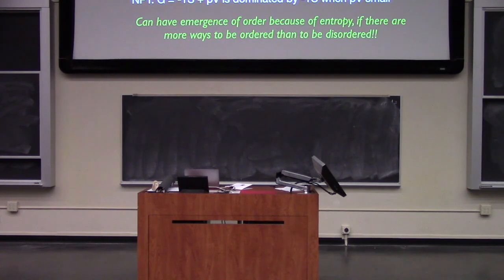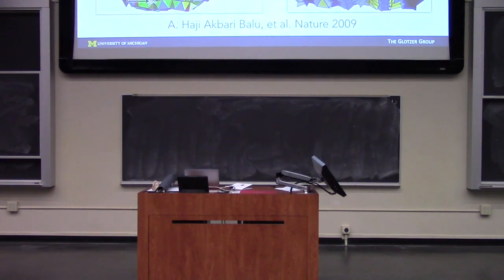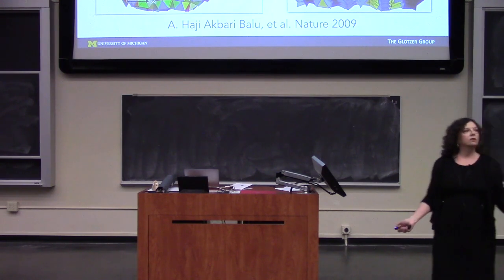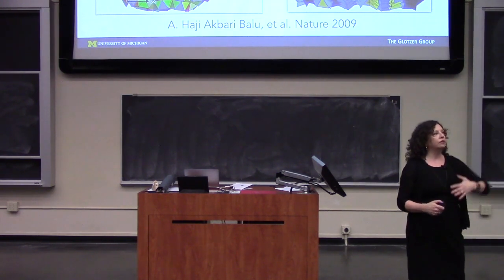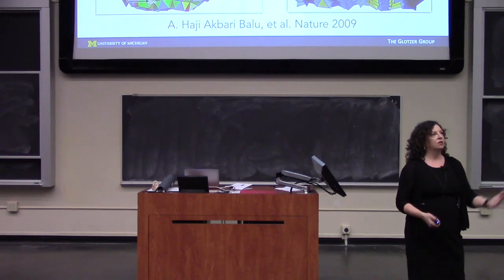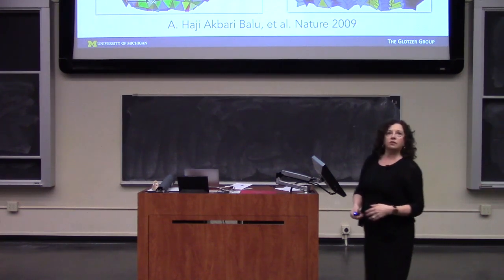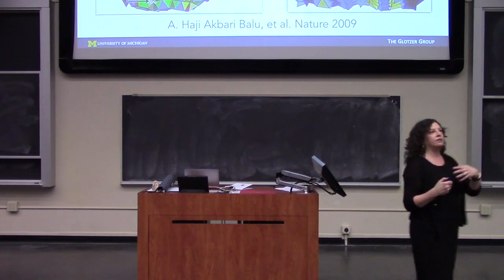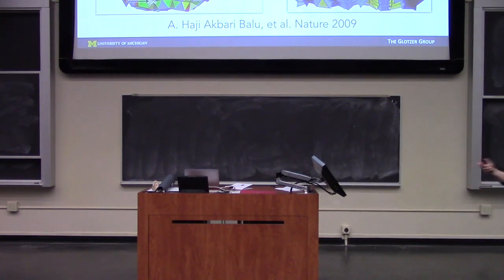So that means an equilibrium for a hard particle system is the maximum entropy state. That means that our system went from a disordered fluid to a quasicrystal to maximize the entropy. And that is what's counterintuitive. So this is what this structure looked like that Amir showed me. We usually think of entropy as being associated with disorder, and we think that things that are more disordered have more entropy. Well, that's only in the colloquial sense. What it really means is you have more entropy the less you know about the system.